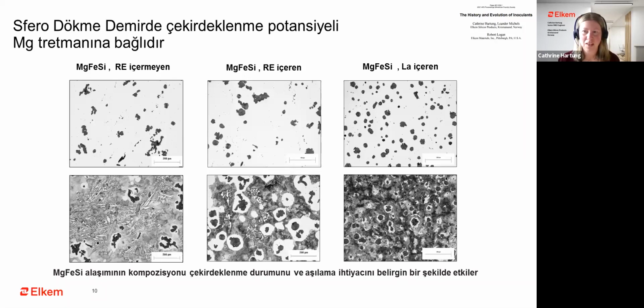So of course, the need for inoculation is very different depending on which magnesium ferrosilicon treatment you have started with in this case. So this composition of magnesium ferrosilicon can significantly affect nucleation conditions in ductile iron and the need for inoculation.